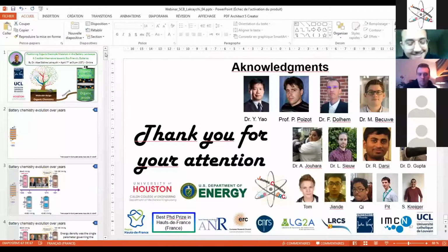Sorry, and just maybe about the bulky substituents that you could put on your compound. Yes, I see. This is interesting because, as I said, you have two different redox mechanisms. Sometimes you use cations for charge compensation, and those cations could be lithium plus, sodium plus, magnesium plus, potassium plus. The molecular weight of lithium plus is only 6.941, so it's low. Sodium plus is 23.